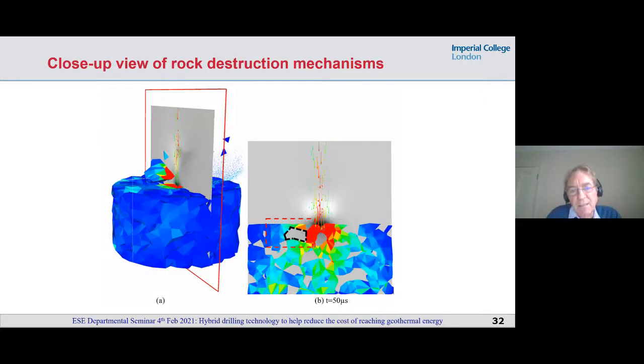And I wanted to just show you this. If you take a nice slice and then look at what the two fields are capturing, you can see a slice through this domain. And that figure on the right hand side is showing in the grayscale the fluid pressure. So for example, just underneath where that hammer effect is happening is this black, very high pressure acting on the granular grains of the solid, and that's why the solid is now expressing the tensile stress in red. And I'd just like to draw your attention to a pore that's just on the shoulder region of that piece of sandstone. And in fact, what we can see is the fluid flow going into that pore space.